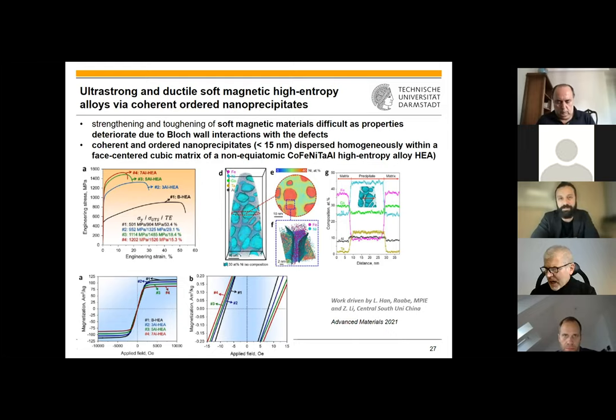Interesting question. And indeed, we are working on iron nickel because it's an absolutely fascinating topic. But of course, there's a big but. I showed in the beginning that we need to transfer, and that is a huge challenge. If we manage to get L10 iron nickel in the ordered phase, nobody has shown that. If that was possible, then you still have the big challenge to make an appropriate microstructure. To get the thermodynamic compound with the intrinsic properties, which might be interesting, is one thing. But to actually make a magnet which has the right microstructure to have significant coercivity is a huge challenge.